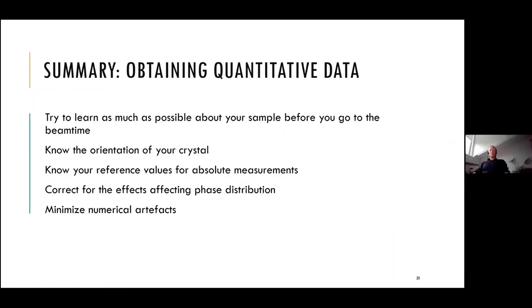So, summary for this part: obtaining quantitative data is possible only if you try to learn as much as possible about your sample before you go to the beam time. It's still not giving you a direct answer to all the questions, but you will know where to look for these answers. You should know the orientation of your crystal. You should know your reference values if you want to get some absolute measurements, like the exact lattice spacing. You have to correct for effects which affect the phase distribution after the reconstruction. And additionally, you should think about minimizing the numerical artifacts coming from the phase retrieval itself.